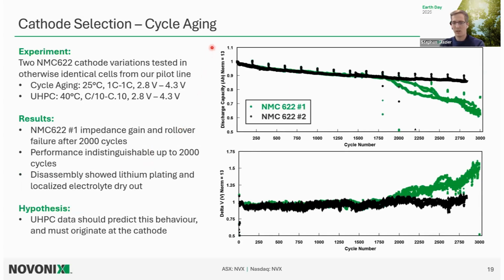A really simple example here is two NMC materials that we were testing. These data are shown from our pilot prototyping line, where we made 1 amp hour pouch cells with the exact same anode batch, the exact same electrolyte batch, and assembled at the exact same time. The only difference was the two NMC active materials. You can see here over 8 months of cycling, there was no real warning of anything different between these cells. They're both fading the exact same way.